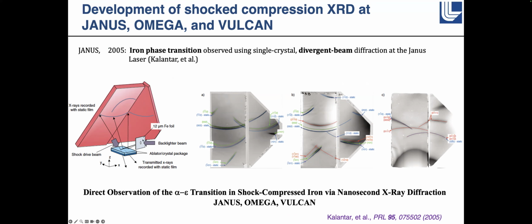Here we had an iron foil that we put about 2 millimeters away from our sample. We shined other lasers on the back of the sample, so we drove a shock through the sample. We focused a backlighter beam, a kilojoule backlighter beam that was focused tightly, 300 microns or so, which basically makes a very hot plasma, which then emits. You strip all of the electrons off of the iron foil until you've got basically 2 electrons left, and then you look at the K alpha, or it's a helium alpha, but it's the excitations when you excite and cause fluorescence of those helium iron. It's a helium atom with an iron nucleus, and that emits a relatively monochromatic, bright X-ray source.